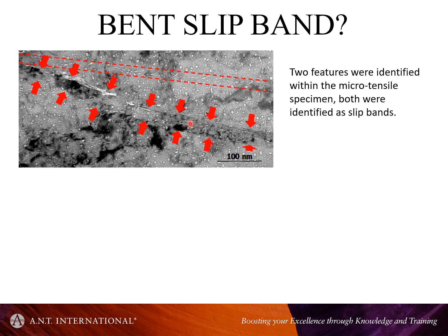And at the same time, this isn't a 1-1-1 slip plane. Here you see a shear band which, as we've described, could be twinning or it could be an actual dislocation band on multiple different planes because of the climb of the dislocations, but it's not aligned with this feature.